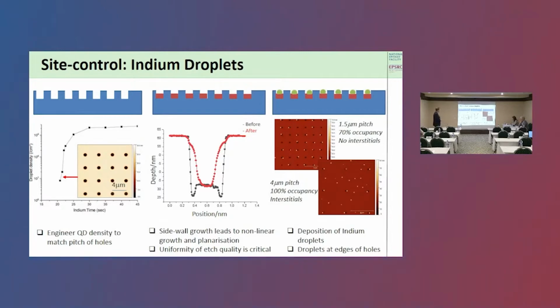And this is important because we make patterns for the nanoholes, and if we can match the density of the dots to the density of the pattern, we increase the chances of achieving site control of the droplets into the pattern.